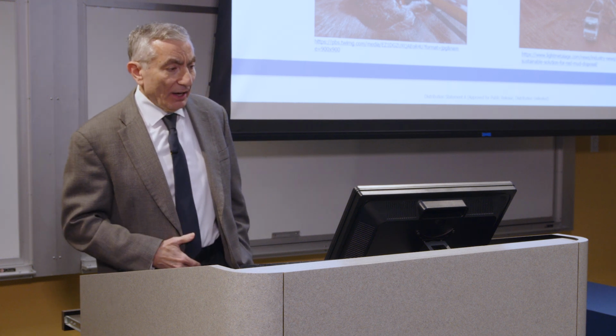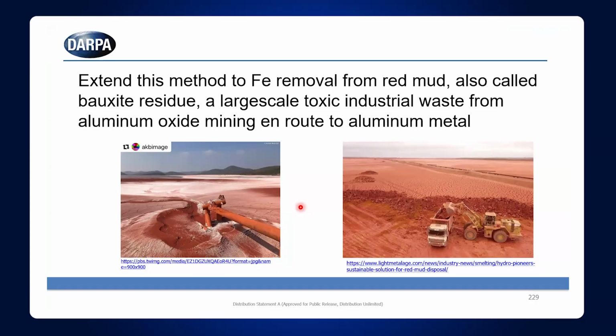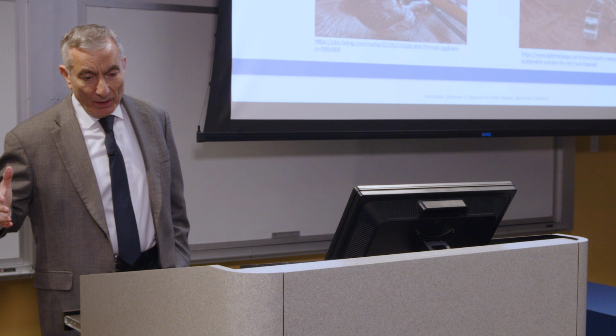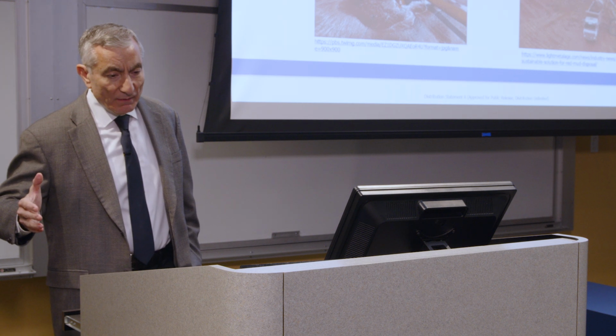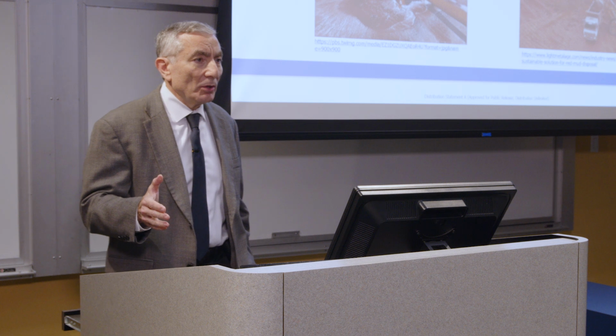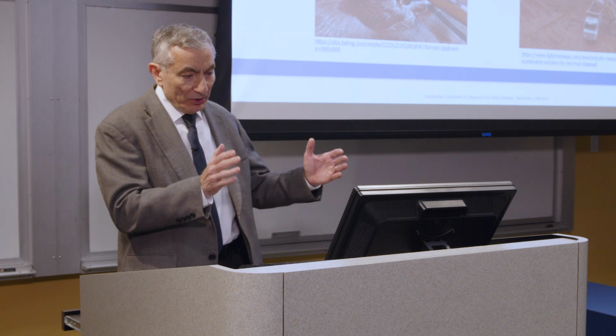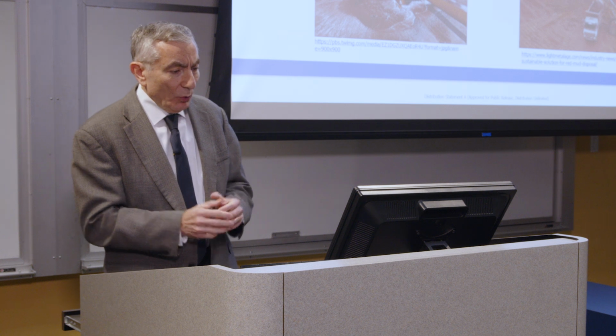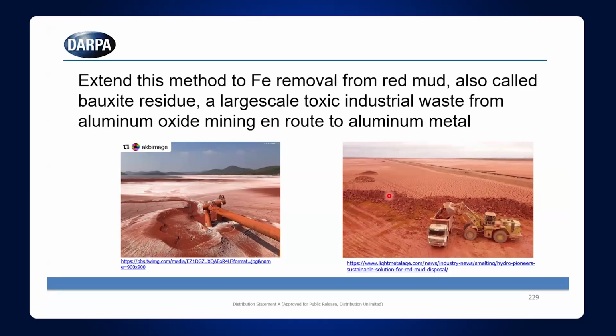So we can extend this now. This method, remember we talked about bauxite residue or red mud. The big problem is removing iron from the red mud. The reason this looks red is because it has iron in it. Hematite is a form of iron oxide, and it's red. That's why it's called red mud. It's a bauxite residue, so you're taking aluminum oxide, which is bauxite, and then you reduce the aluminum with that sacrificial electrode with its power plant, but you're left over with some aluminum that's very hard to separate from iron.